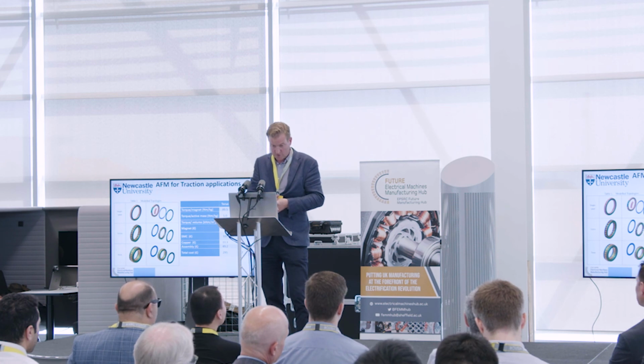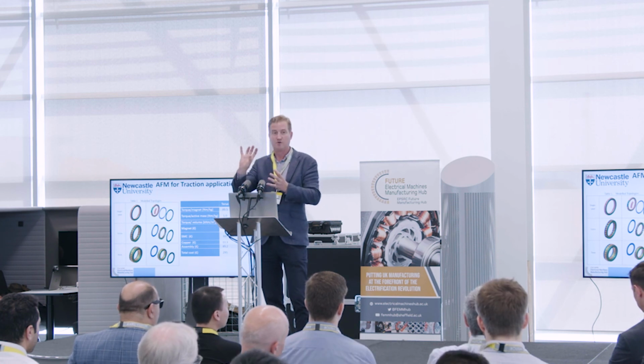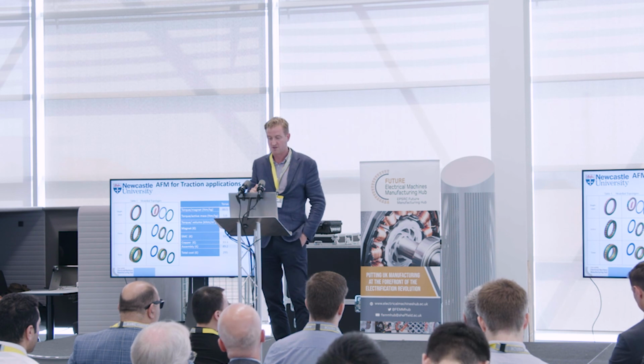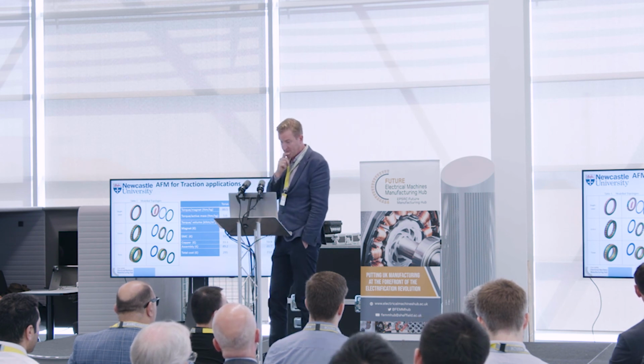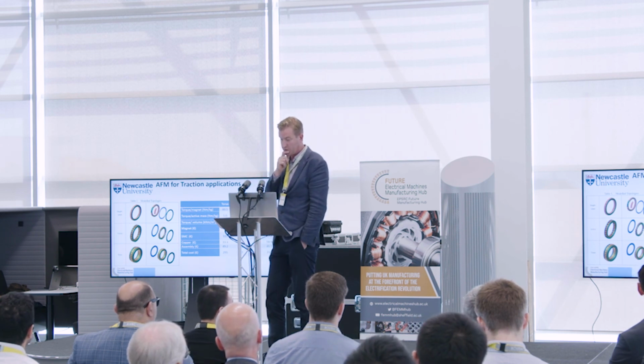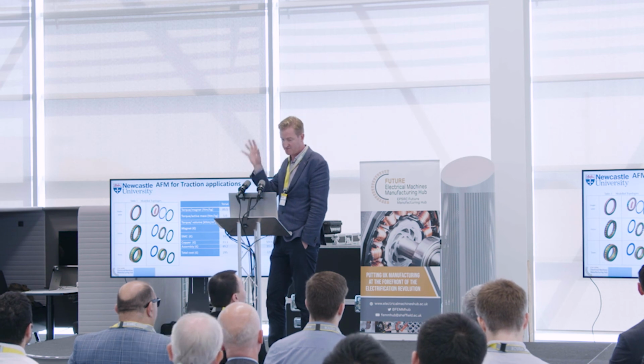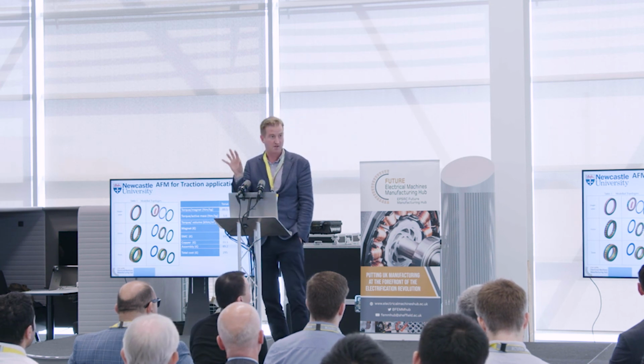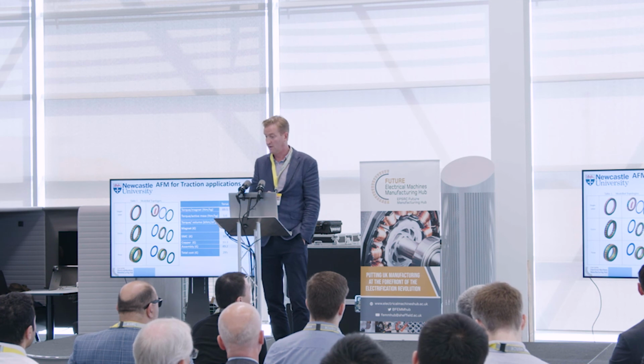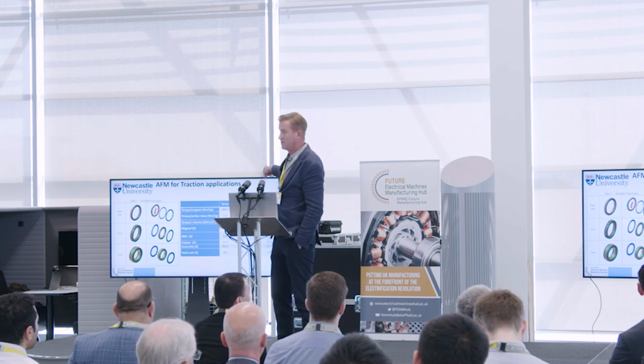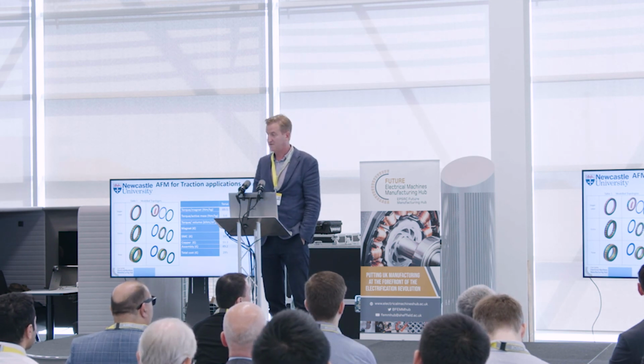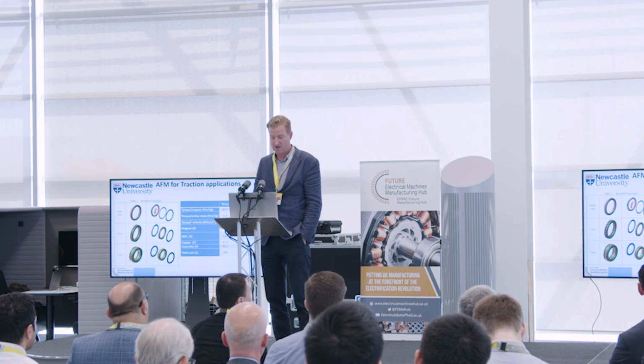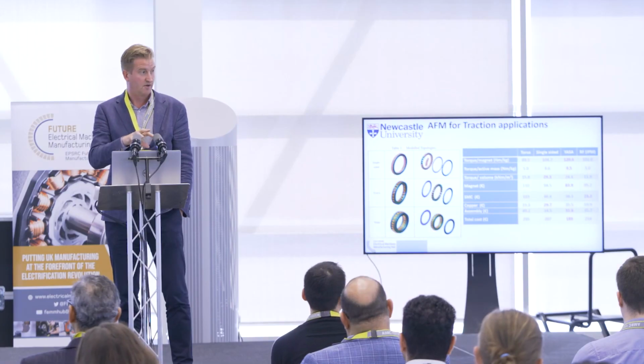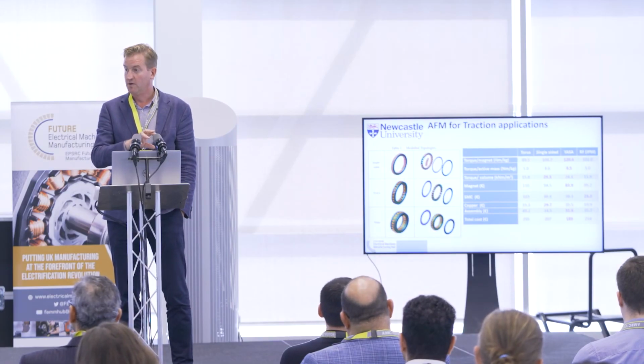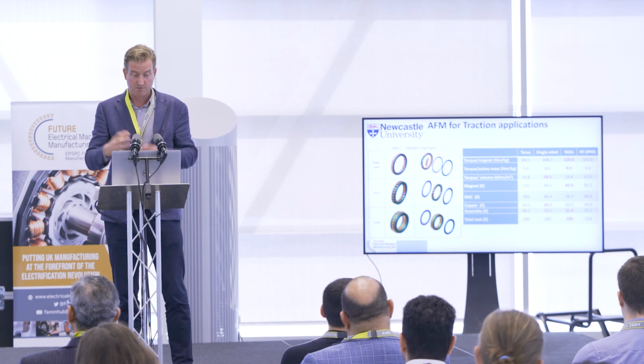We've also looked at the torus version of that, where the coils are effectively turned by 90 degrees. When we look at the various stats there, so torque per magnet kilogram, torque per active mass, cost, and so on and so forth, the YASA topology does come out really rather well. You see the red numbers there are the maximum or the target. The single-sided axial flux machine comes out quite nicely on torque per volume, and it's quite a simple structure.